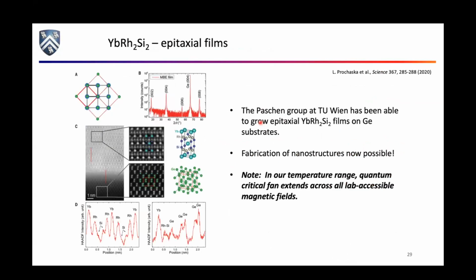What makes this possible is the fact that we can pattern wires out of the strange metal, and we can do that because we have these lovely epitaxial films that the Paschen group. These are epitaxially nice. They're grown on germanium, which at low temperatures is nice and boring and insulating. And like I said, in our temperature range, the non-Fermi liquid regime extends across all available field space that you can get to in the lab.